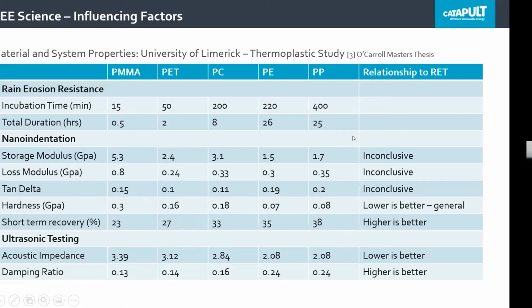They then compared this to nano indentation measurements. What you would think would be important, like your storage modulus, your loss modulus, your tan delta, the relationship was actually found to be inconclusive. They did find some relationship with hardness, which has also been noted by coatings manufacturers, where in this case lower is better. But in particular, they found that the short-term recovery matters. For those who don't know, nano indentation measures the initial depth of the indentation minus the almost instantaneous recovered depth from the unloading curve. I'll come into that a bit more later. They found that the higher the short-term recovery, the better.